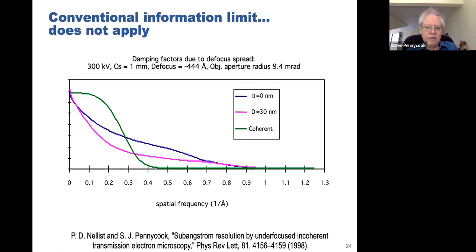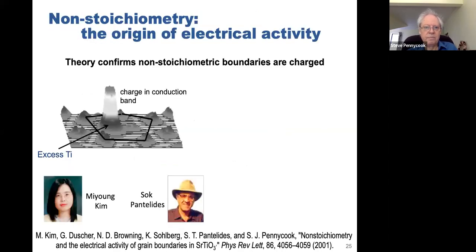And we realized, in fact, that the conventional resolution limit in a TEM, you'll cut it off with these damping factors. But in STEM, it's really quite different. The high resolution information is not cut off by things like energy spread or defocus spread. It's the mid-range frequencies that are damped. So very different behavior. High resolution information is preserved.